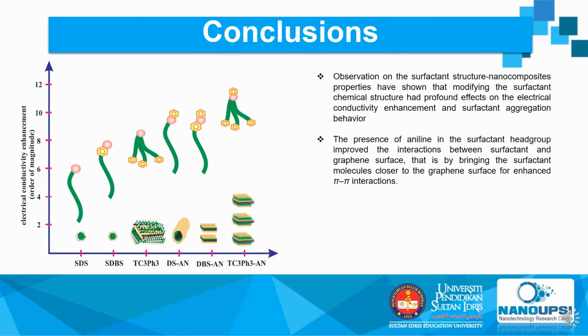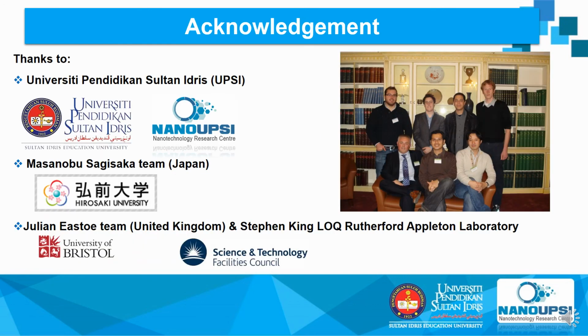For conclusion, observation of surfactant structure and composite properties has shown that modifying the surfactant chemical structure has a profound effect on electrical conductivity enhancement and surfactant aggregation behavior. And the presence of aniline in the surfactant head group improves the interaction between surfactant and graphene surface, that is, by bringing the surfactant molecule closer to the graphene surface for enhanced pi-pi interaction.